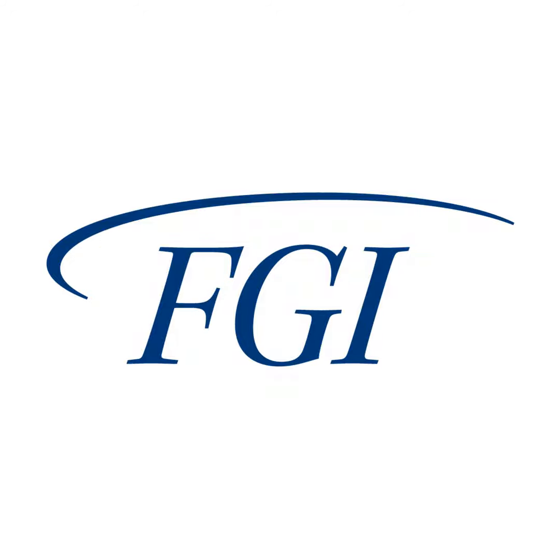Great. Next question, GCL without a geomembrane is being spread out for a final cover system where confining pressure is an issue. Is it also used in leachate surface impoundments that have very little confining pressure when they have only about a foot of leachate on top of the geomembrane? So I would say, during the webinar, the issues that we referenced were related to GCLs left under an exposed geomembrane that had no soil cover at all for an extended period of time, months or years. In those situations, that exposed geomembrane can undergo huge temperature changes, which can cause problems for the materials underneath it. But it sounds like in the applications being described in this question, the liner won't be exposed in the same way. It sounds like there's going to be some minimal amount of soil cover, and that is sufficient. Whether it's a foot or two, it should be sufficient soil cover.